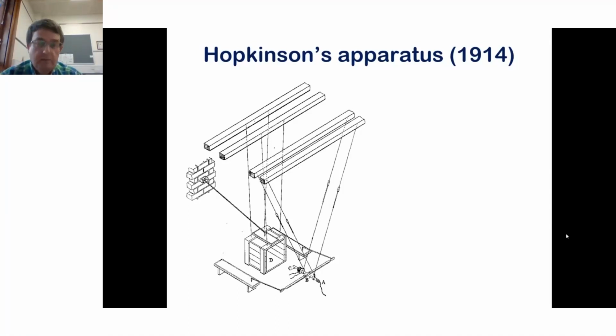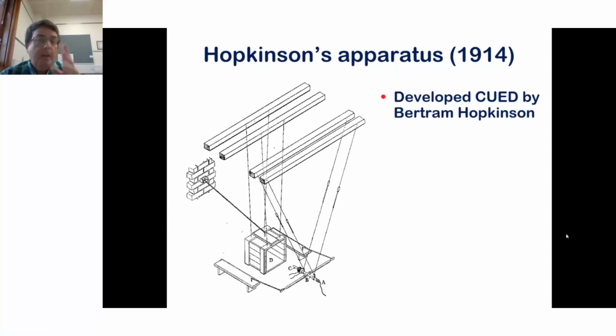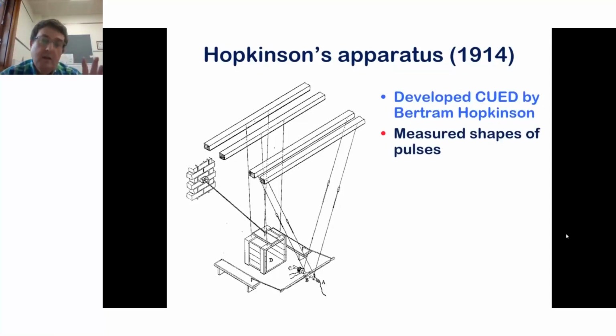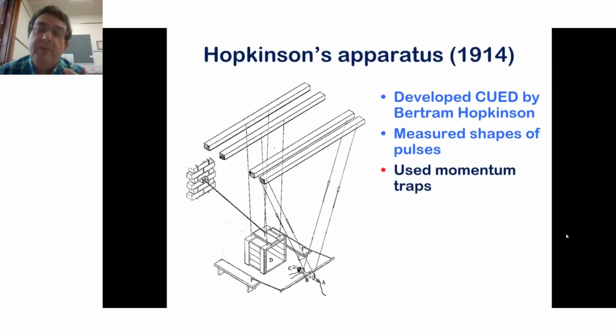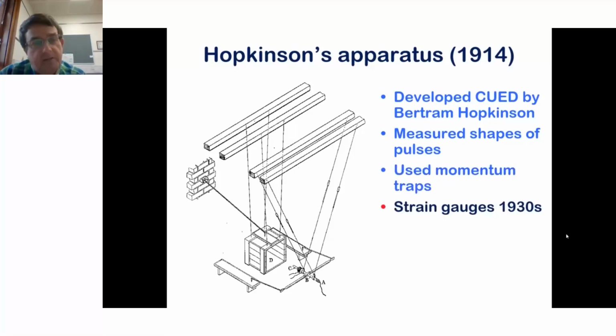Very simply, Bertram Hopkinson at the Cambridge University Engineering Department measured the shape of pressure pulses using this apparatus, because that little block of material C, he can change the length of it, and he can trap different amounts of momentum, different amounts of energy by changing the length of that momentum trap. And this is well in advance of using strain gauges. What he does is the impulse, the impact at point A, causes that momentum trap C to jump off the end of the rod into the tea chest D. The tea chest D is suspended like a pendulum, and it moves because of the energy delivered to it by that momentum trap.